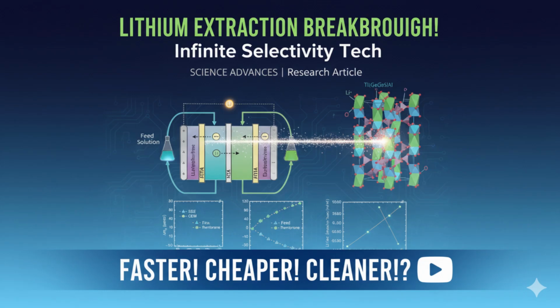Okay, what about membranes? Filtration membranes are used everywhere for separation. Surely they can handle lithium. They can, up to a point. Conventional membranes, like nanofiltration or reverse osmosis, are pretty good at separating things based on size or charge difference. So getting lithium, Li+, separated from magnesium, Mg2+, which is divalent and often larger when hydrated. Yes, membranes can do that reasonably well. But the absolute wall they hit is separating ions that are very similar, specifically monovalent ions, lithium versus sodium, Li+ versus Na+. Because they're both +1 charge, similar size.